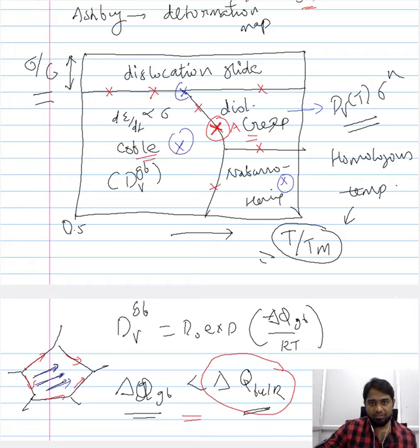If you have a point here, then instead of two different creep mechanisms being operational, we have three. Say for instance, at this point B, you have Coble creep, dislocation creep, and dislocation glide operational. At this point here, you have dislocation creep, Nabarro-Herring creep, and Coble creep operational. And at these points, they are operating simultaneously. So to calculate the overall creep rate at this point, it would be the summation of the rates rendered by all the creep mechanisms.